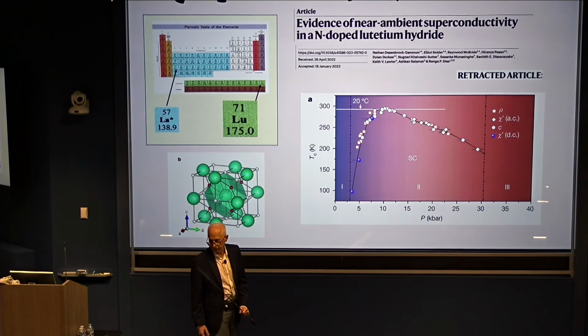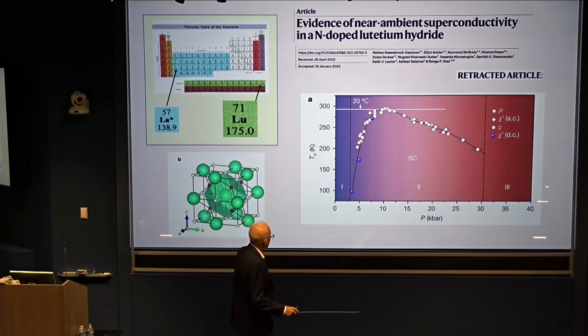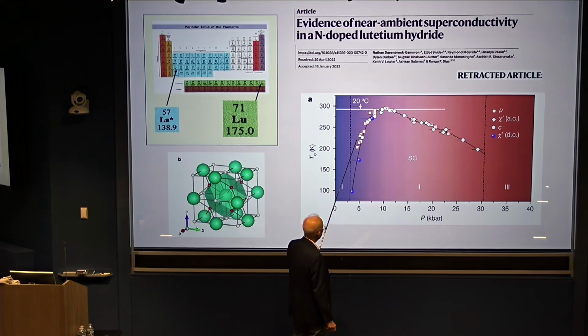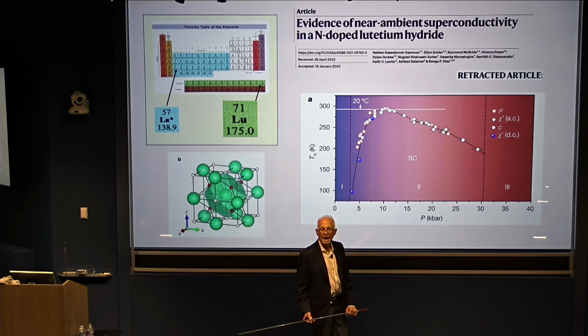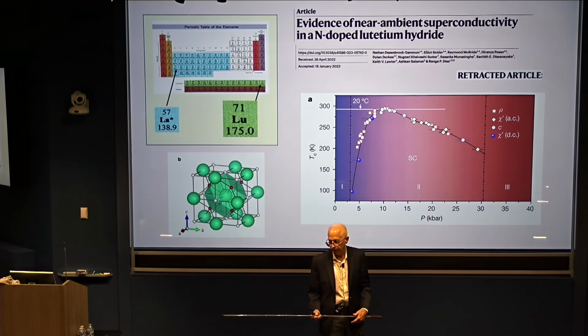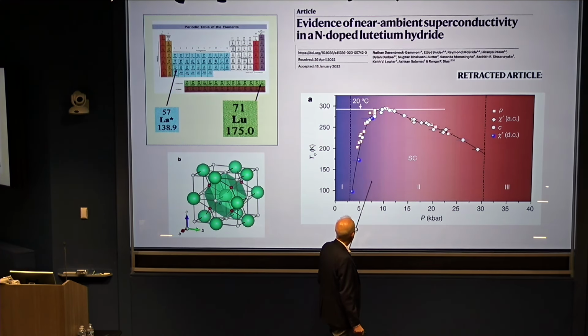So the second ternary I want to tell you about is one that's been controversial, and that is the work on lutetium, nitrogen, and hydrogen. And this was work by colleagues at Rochester. They announced in March of '23 that they had found evidence for some kind of superconductivity at approaching room temperature, really in the vicinity of room temperature, but now at 2 orders of magnitude lower pressure, pretty close to ambient, 1 GPa or 10 kilobars.